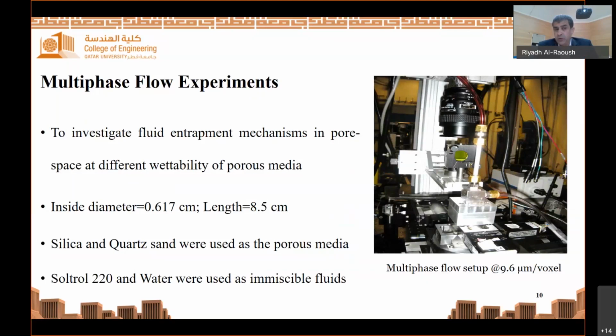The cell that we used was a column with an inside diameter of about 6 millimeters and a height of about 8.5 centimeters. The column was connected to tubes and pumps that allow fluid injection into the cell, and different sands were used to represent natural porous media systems.